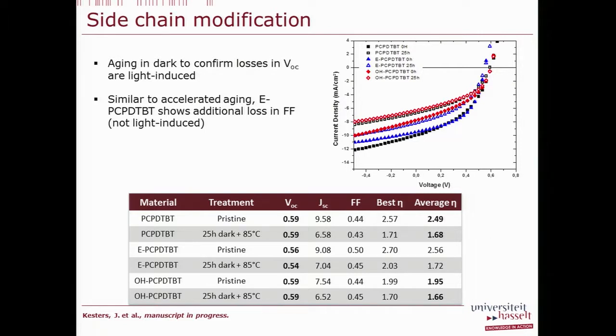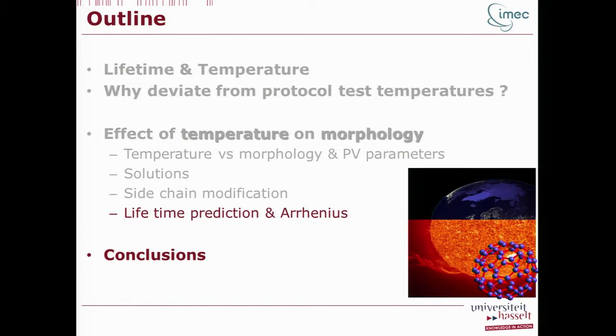And there we have seen that aging in dark confirms that the losses in VOC are light induced. So the change of VOC is really due to the application of light, and the change that we've seen in the fill factor is not light induced. But this has to be studied further. So as a last point, I would like to come to the aspect of lifetime prediction and Arrhenius.